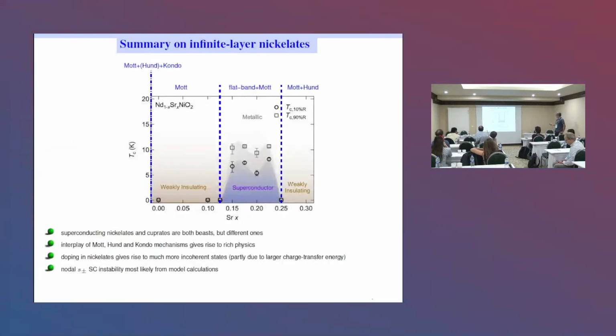So, but then we have this flat band picture when we go to the superconducting region, and then we have even more Mott Hund physics in this weakly insulating region. We could explain this weakly insulating behavior seen in the overdoped region by these Hund-like correlations of this two-orbital flat band coming up and the x²−y² spin. So that is a different regime. You could say this is a bit Nickel-tight kind of, and this is a bit more cuprate kind of, although not superconducting. They meet in between with this flat band scenario giving rise to the superconductivity.